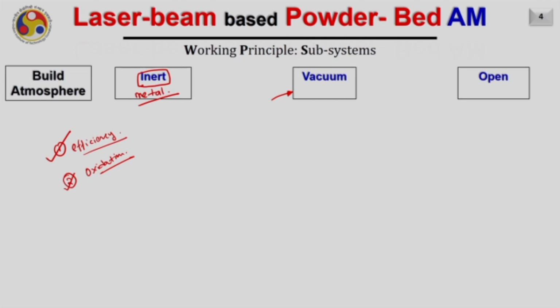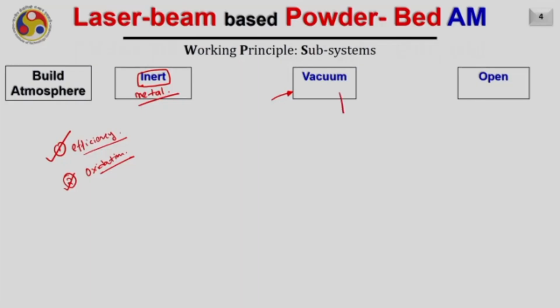This system is very applicable for metals that are very reactive with the gases available in the air when the temperature of the powder particles is high. Another importance of vacuum is that it minimizes convection heat transfer in the powder bed chamber. As a result, the temperature of the entire bed may remain uniform, and the chances of residual stresses will also reduce, as the whole bed will be at a particular preheated temperature. Commercial machines with vacuum may be available soon, but these are still under development.